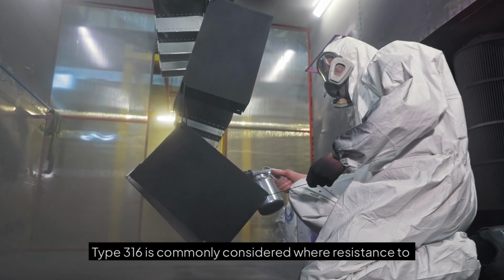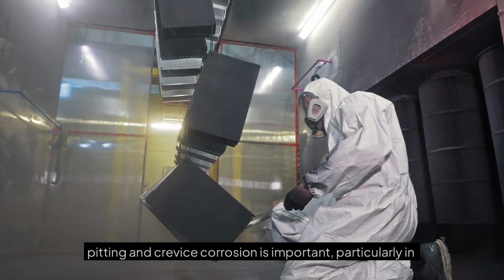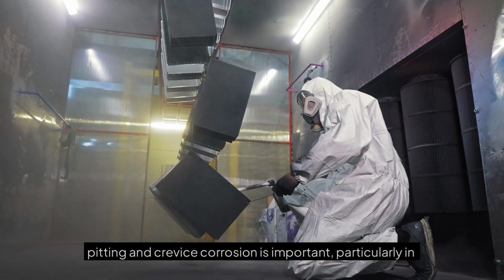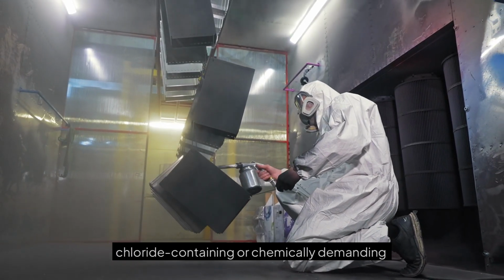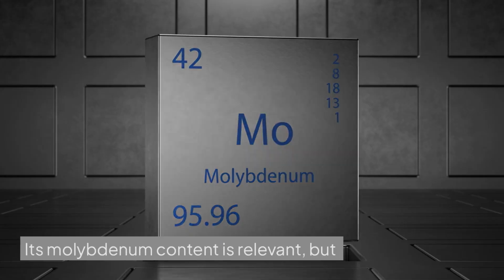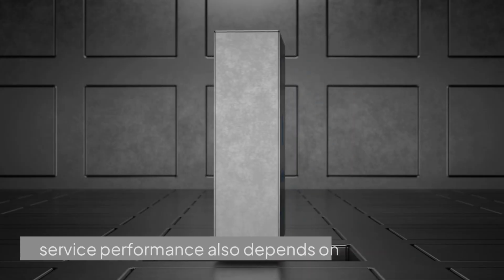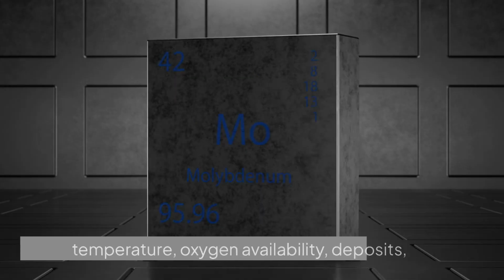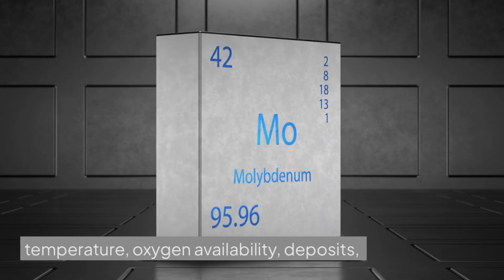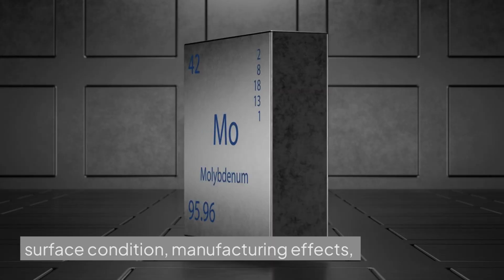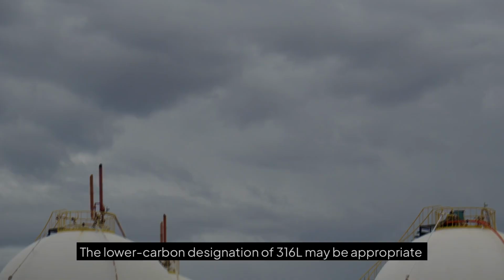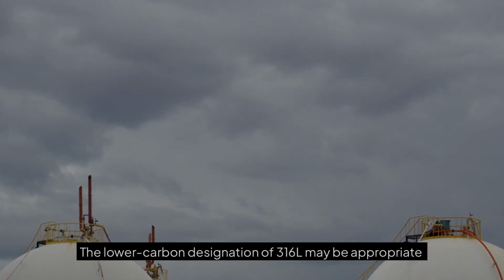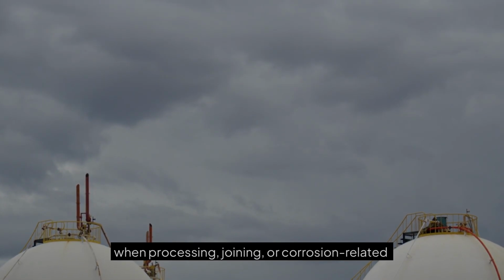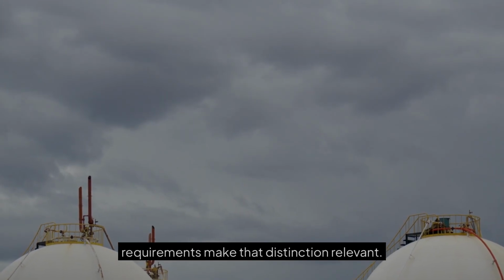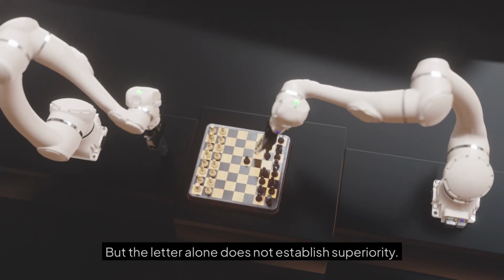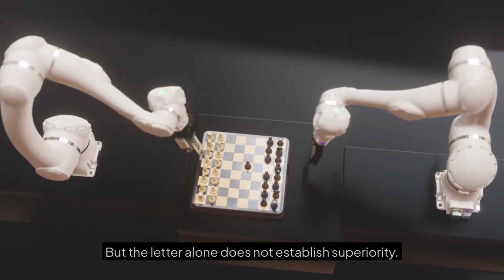Type 316 is commonly considered where resistance to pitting and crevice corrosion is important, particularly in chloride-containing or chemically demanding environments. Its molybdenum content is relevant, but service performance also depends on temperature, oxygen availability, deposits, surface condition, manufacturing effects, and assembly geometry. The lower carbon designation of 316L may be appropriate when processing, joining, or corrosion-related requirements make that distinction relevant. But the letter alone does not establish superiority.